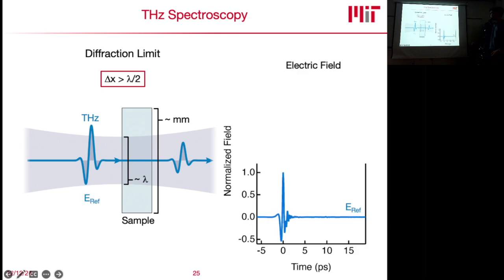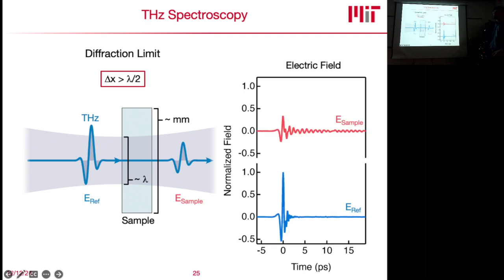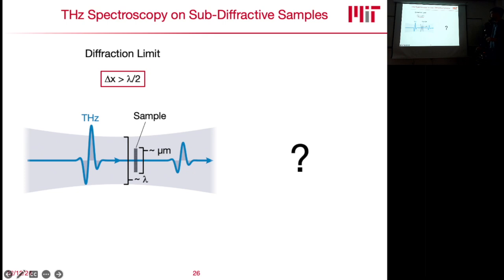Typically what you then measure is you send in a reference field, which you measure, and then you measure the field transmitted through your sample. If something interesting happens, you will get an attenuation of your terahertz amplitude, and you will also additionally get coherent oscillations, which usually hint at coherent dynamics in the system and collective modes. This is typically how people do terahertz spectroscopy. So now for small samples, how does the situation change? What happens now if your sample is much smaller than your diffraction limited spot?